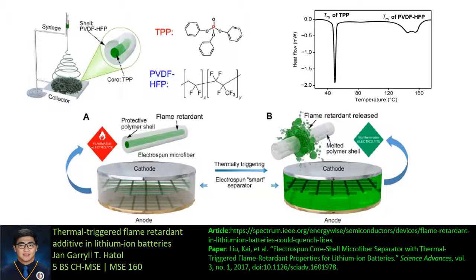The most important part of this slide is the top right part, which shows the melting point of pure TPP and PVDF-HFP, which is the coating of the core shell. The TPP shows a melting point of 50 degrees, while the PVDF-HFP shows a melting point of 150 degrees. This means that the PVDF, which coats the TPP at this point, will only release the TPP at around 160 degrees. A demonstration of what will happen when this temperature is reached is shown on the bottom half of the slide.